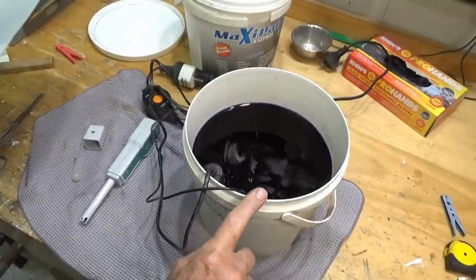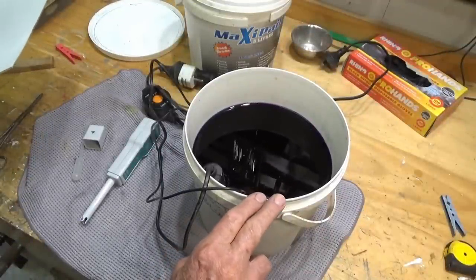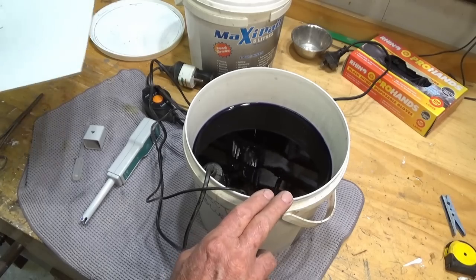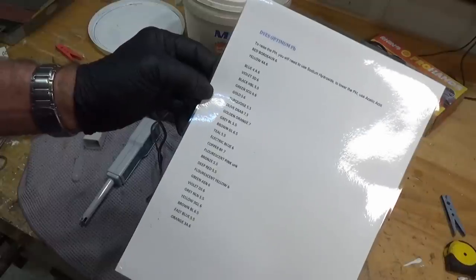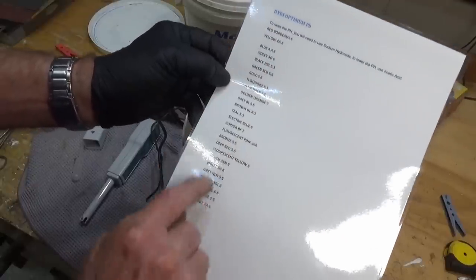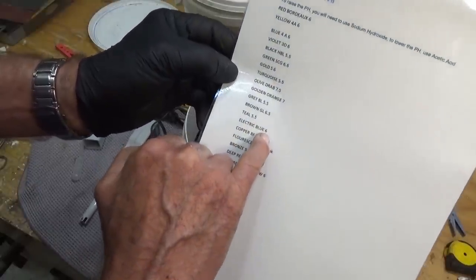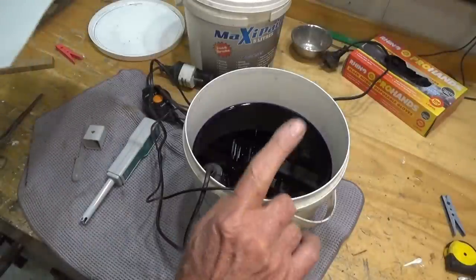This is the dye that I'm going to be using on these parts. Now this is a Caswell dye called Electric Blue, and I was browsing through the Caswell forum a while ago and I came across this document here, called Dyes Optimum pH, and I'll put a link to this in the description of this video. But it lists all of the Caswell dyes and gives you the optimum pH for that particular dye. So in the case of Electric Blue, we're looking for 6. And we're going to check this in a minute.